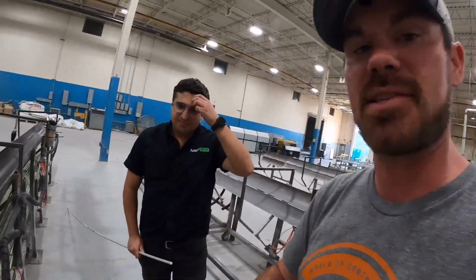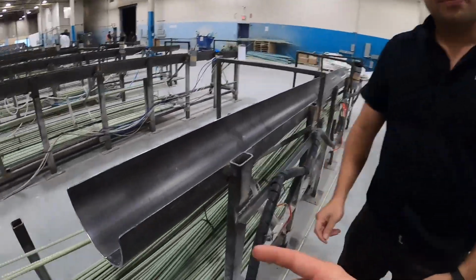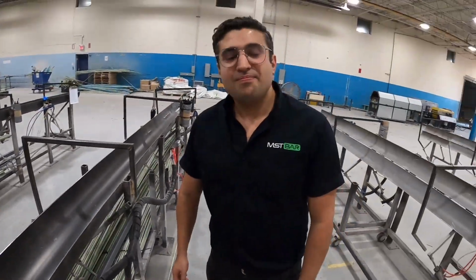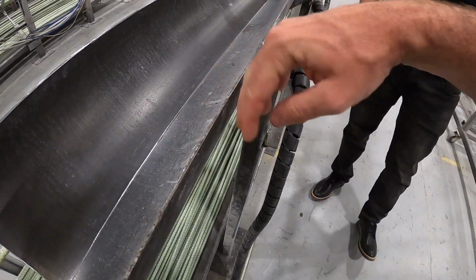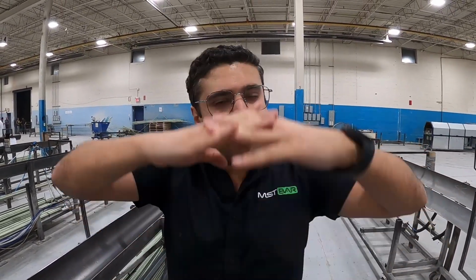Exactly. And back to the concrete has to bond to it. If it was a slick surface like this, the concrete does not bond well. Exactly. You'll see a small crack from the concrete to that metal where it's separated because of the shrink in the concrete. That's very true, Matt, but it's not only that one. The other problem is when you go on a cyclic loading, when you have a slab that's going over millions of cycles, these bars, if they don't adhere properly, they start to move. As soon as that rebar starts to move in a concrete, you're gonna get a shear crack. Your punching shear and your shear capacity goes down. So the bond strength is the key for the proper rebar, and it's almost the most important thing you can have.